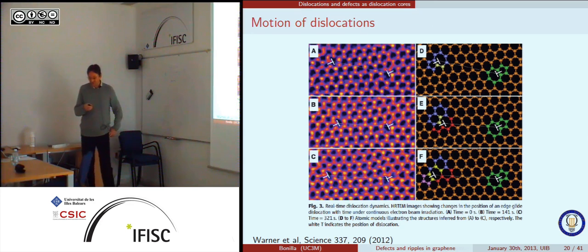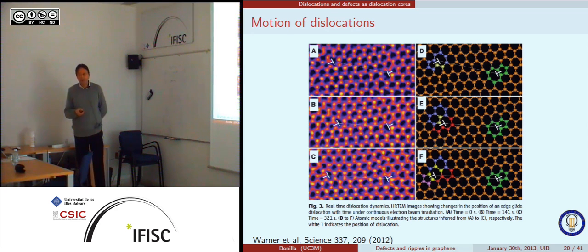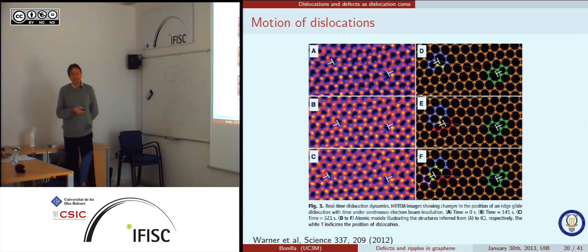Now, all of this was done with a high-resolution electron microscope that was aberration corrected, and then later people used a monochromator, so they send a monoenergetic beam of electrons, which was not the case of the previous ones, and they got a lot more resolution out of it. So these pictures were taken at Oxford. And they show two dislocations, so two pentagon heptagons. The Burgers vector is directed on this line. So this is one example in which you have the cleaner interpretation. These are the data.